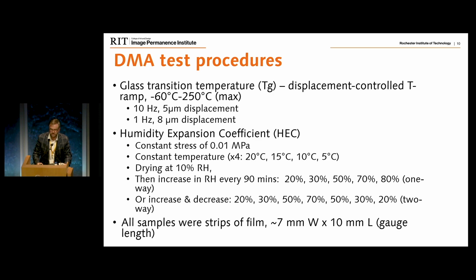So what are we doing in the DMA? Those procedures for those 2 tests, you can see here. Glass transition is a very simple displacement control temperature ramp. The maximum is used for pure acetate. Then for others, we were lowering the maximum down a little bit because we got the samples melting. And the humidity expansion coefficient, that's a little bit more complicated. What is happening there, we are applying a constant stress to the film in the clamps, stabilizing the temperature at one of those 4 levels, as you see here.